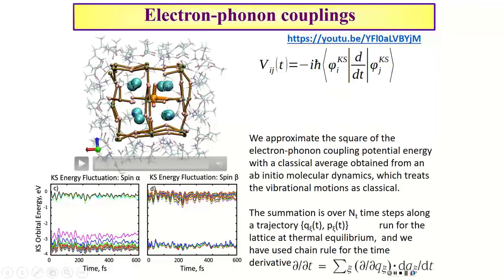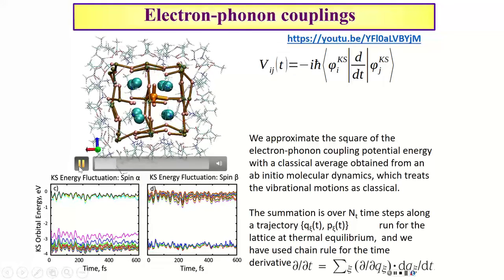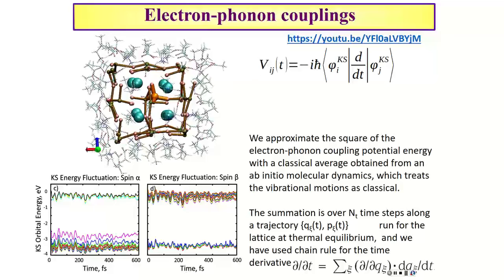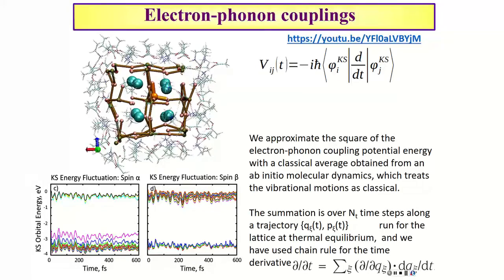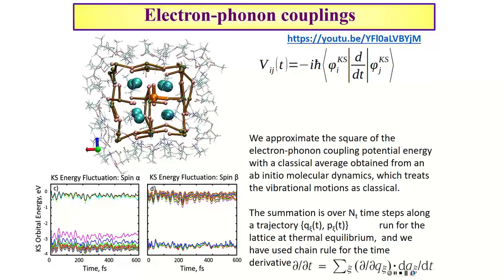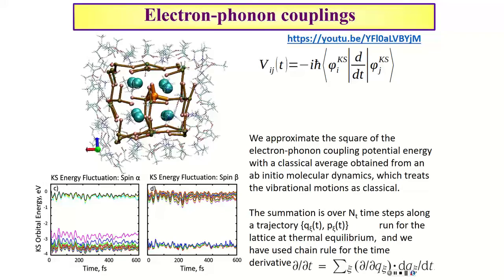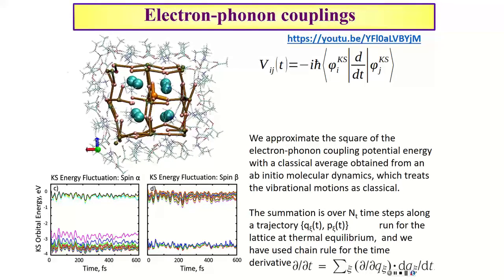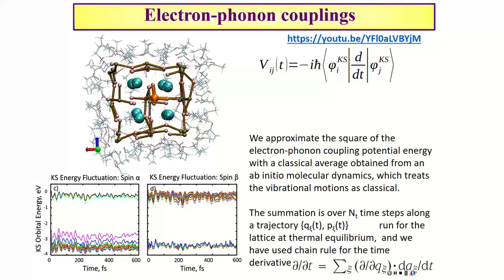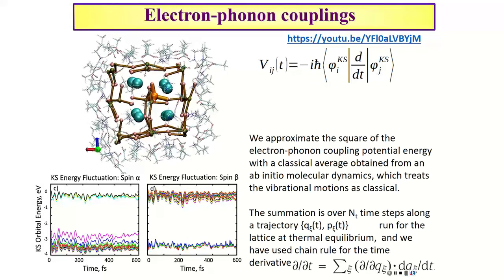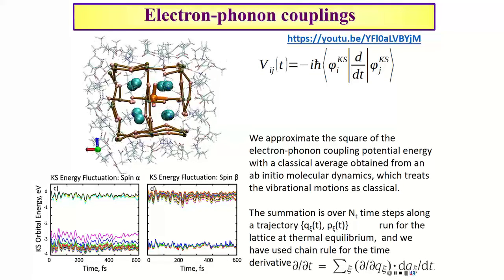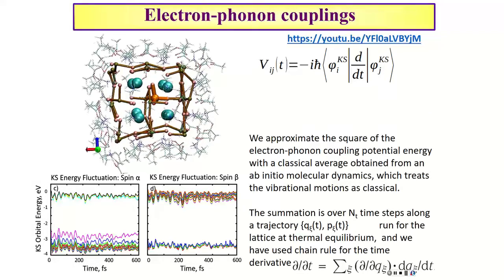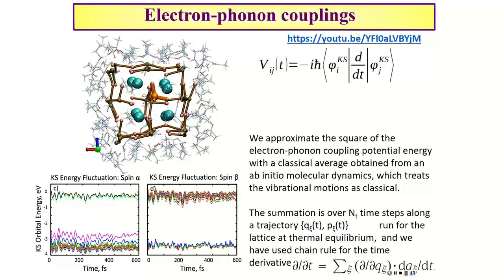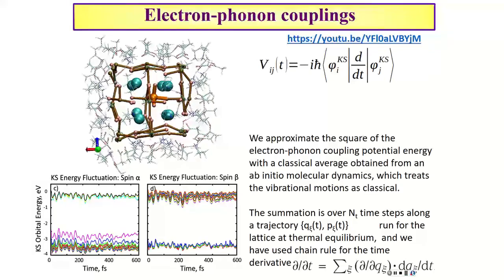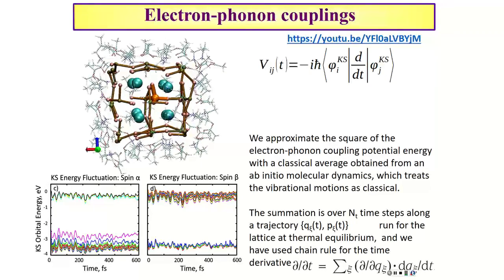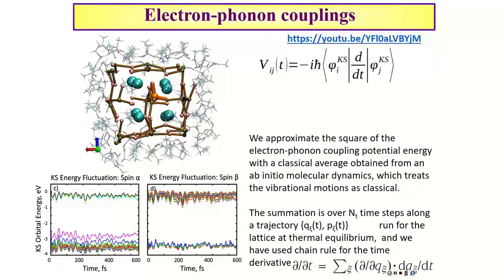So there was an attempt to do the standard practice for non-adiabatic dynamics: go along the trajectory, see how the orbital energies change in time, how the couplings develop along the trajectory, and then plug it into the standard protocol for electron dynamics and emission. What was potentially dangerous is that originally the doping is set up to be octahedral, but along thermalized molecular dynamics, it prefers to become tetrahedral. So it breaks symmetry inside this structure and prefers to attract four out of six bromines closer and keep the other two further apart. If you do the ground state, it may not be observed, but if you do the excited state, it can be an issue. Not that we need to panic, but to pay attention. Maybe it's a discovery.